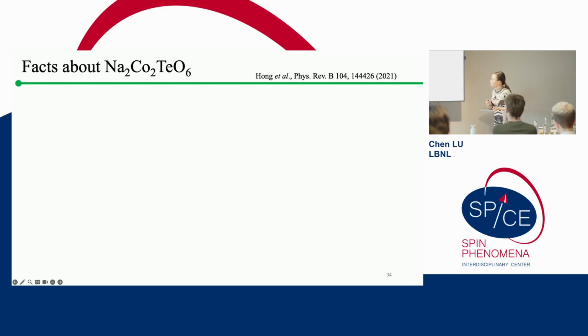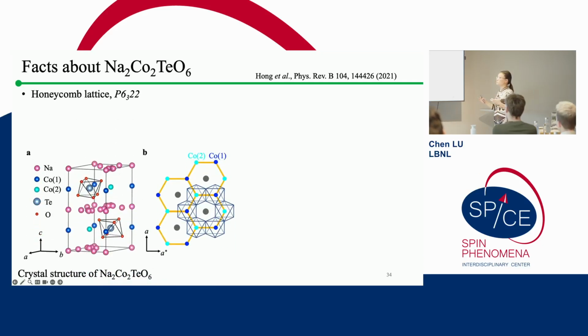So here it goes into the result coming from our group. We actually jumped out from alpha ruthenium trichloride. We found another Kitaev candidate material, the so-called sodium cobalt tellurate, and also tried to study the planar thermal Hall effect inside. So before I show you the result, the first thing I want to show is that there are several important facts about this material.